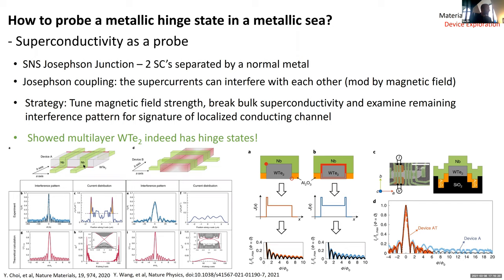It's not bad. But if you were trying to make as high a critical field as possible, it's definitely going to be dependent on the superconducting electrode you choose and its coupling, the transparency of its interface, and the corresponding proximity effect, which is highly determined by that interface. Okay, sure, understand. The second question I had was, this signature of the helical hinge, do you see that on all facets of your tungsten ditelluride crystal, or what happens on other edges, for example?